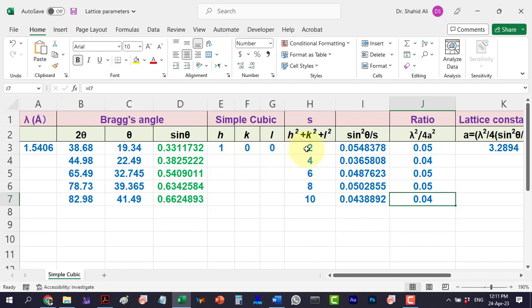Once the structure is confirmed, we can now label the peaks with the Miller indices. To get 2 here, the possibility for hkl is 1, 1, 0. Similarly, 2, 0, 0, then 2, 1, 1, then 2, 2, 0, and 3, 1, 0.